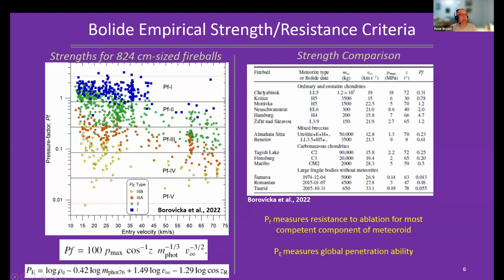So this is at centimeter sizes. You can extend this PF strength comparison to much larger sizes. I'm just showing here a few meteorites that have had their fireballs measured with sufficient precision to measure PF. And the essential point here is that ordinary chondrites have typically these fairly high PFs, meaning they're strong, and carbonaceous chondrites and some objects that we think there are no meteorite analogs that we have in our lab experience have incredibly small PFs. In other words, they completely break up under very low pressure.